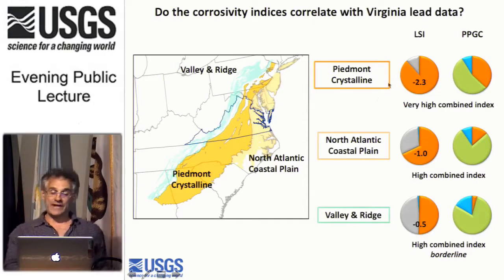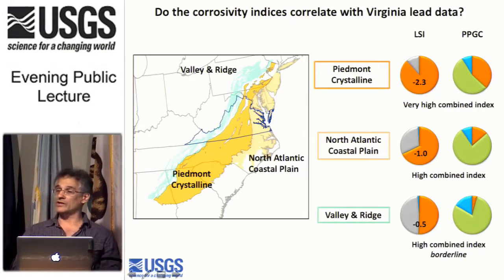Let's take a look at these average values for a second. Negative 2.3, negative 1, negative 0.5. A clear gradient in the average value. Look at the size of that orange slice. There's a clear gradient in how big that slice is. The Piedmont crystalline is the most corrosive, the Valley and Ridge least corrosive, North Atlantic coastal plain intermediate in Virginia.